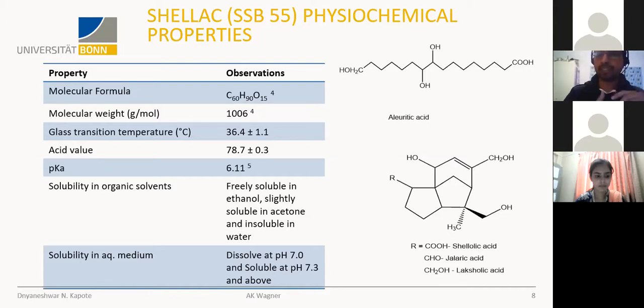Then we can see from the solubility in aqueous media that the real challenge with shellac is that it starts dissolving at pH 7, and it is completely soluble at pH 7.3 and above. So how can we use shellac in a form that can achieve supersaturation, maintain that supersaturation, and achieve solubility enhancement? This is what I will take you through.